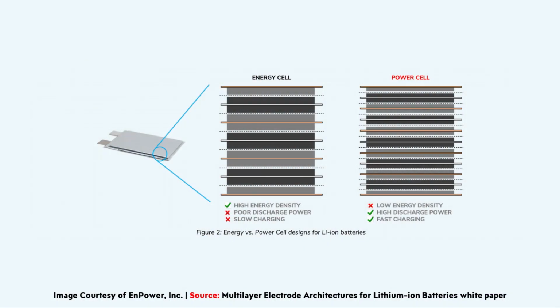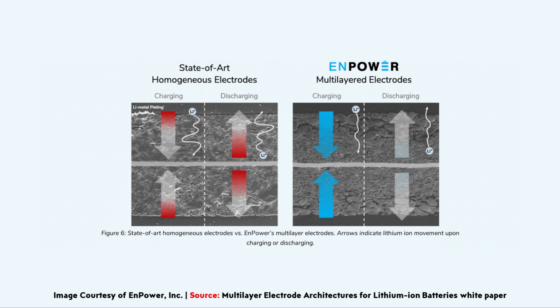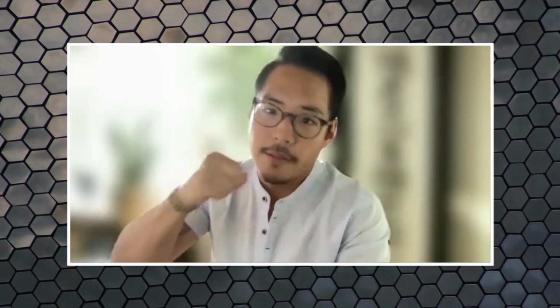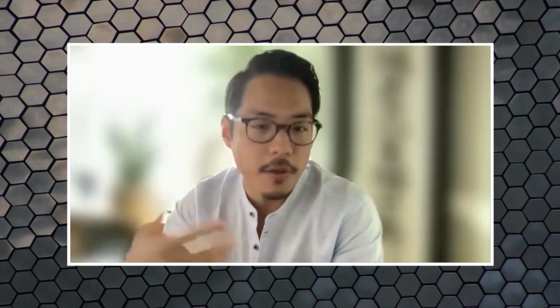On the other hand, you can make really high energy density electrodes by making those electrodes really thick, also compacting them to really high densities. But naturally, lithium ions then need to travel longer distances. And they also have a much more tortuous pathway. That's a technical term, the tortuous pathway to make it through and squeeze through the pores of all those active material particles. And so naturally, their rate of movement suffers and your power will fall.